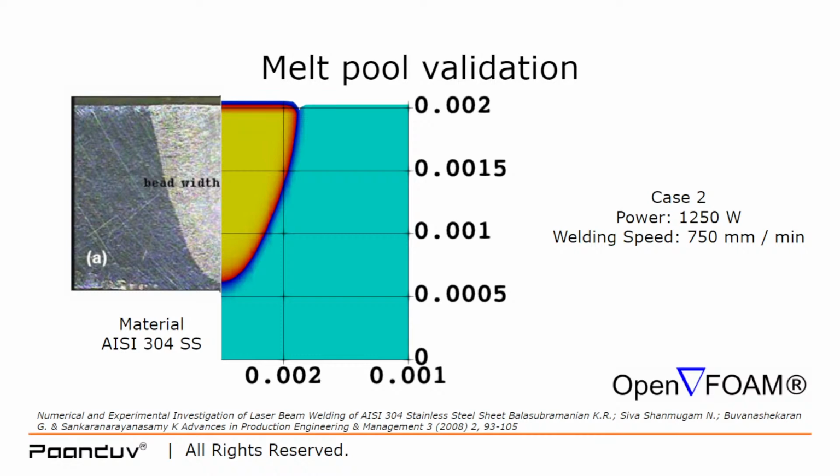Okay, so for example, here we have the experimental image on the left-hand side and the numerical image on the right-hand side, and you can see that the images are quite similar. I want to highlight one more thing: this is not a two-phase system. These are not two-phase problems that we are solving. It's a three-phase problem. The first phase is of course the solid, the second phase is liquid, and the third phase is the inert argon gas, which is typically the case in real 3D printing processes.